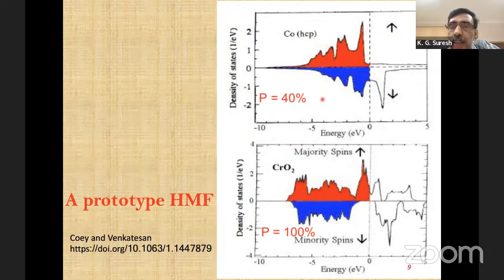Another very important material, an oxide material known again some time back as far as half metallic ferromagnets are concerned, is chromium oxide, one of the oxides of chromium, where you can see very clearly there is a gap at the Fermi level for the downspin band. So it's a practical material, room temperature, 100% spin polarized, which has been used for some applications. It is known for a long time. This is a very standard material today because it was one of the early discoveries in this field.